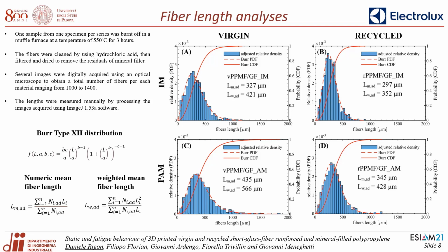The lengths were measured manually by processing the images acquired by using the ImageJ software. As can be seen, the distributions, divided by technology in the rows and by material in the columns, are well fitted by a type 12 Burr probability density function, whose equation is reported in the slide. The numerical and weighted mean values are recorded within the graph, and as can be seen, by analyzing the same technology, the recycled matrix provides lower mean values of the fiber length.